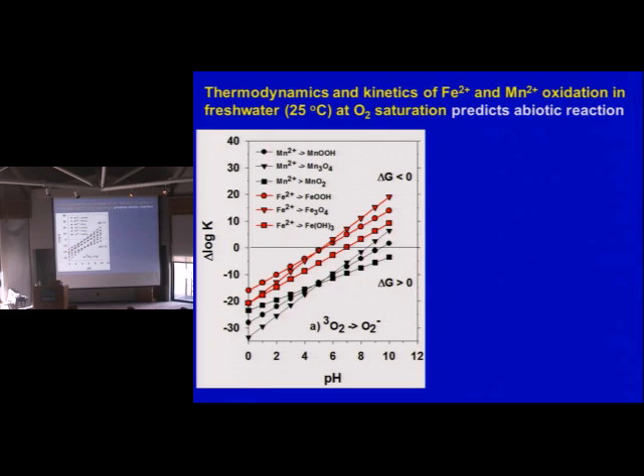Doesn't look it. Now, Peter may tell you that if you look at manganese 2 oxidation, you don't usually see that abiotically till about a pH of 9. And these calculations actually fall that way. All right? So again, this is the first electron transfer step. If you took oxygen going to water, both of these would be thermodynamically favorable. But this is what's controlling the oxidation, the first electron transfer step.